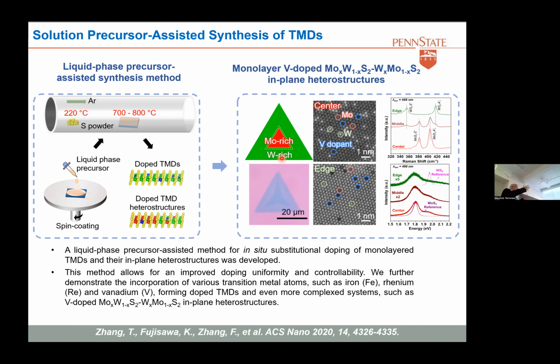If you use your moly precursor and your tungsten precursor, it's just given by the kinetics of the reaction. So the moly will start condensing first, and that grows first. That's a seed, and then tungsten takes higher temperatures. And again, these nucleation sites are usually defective areas, defective points in the substrate of silicon oxide.